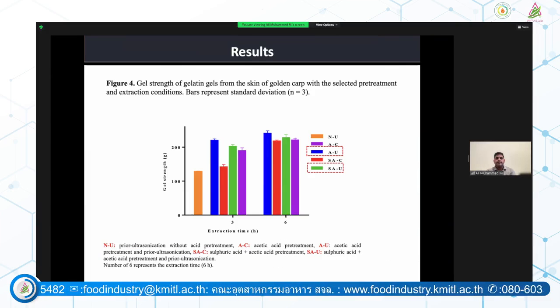And next, coming to the gel strength, after casting the gel, we saw the gel strength was highest with acetic acid, significantly higher compared to all the samples, followed by the gel strength of sulfuric acid extracted at 6 hours. So we concluded that for the extraction time, even though we combined acid and ultrasound, 6 hours is the ideal time for extraction.